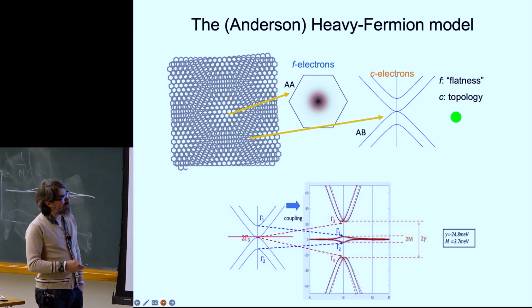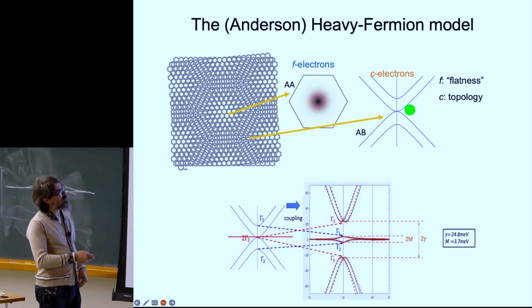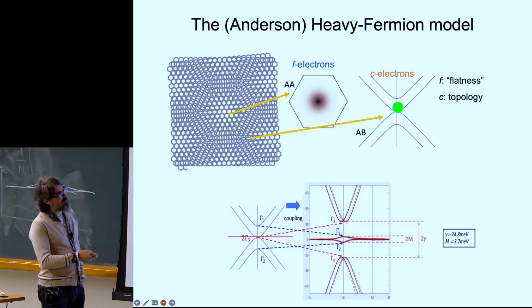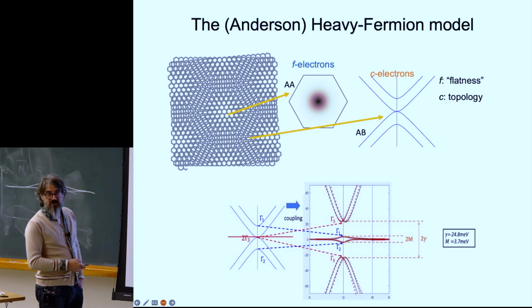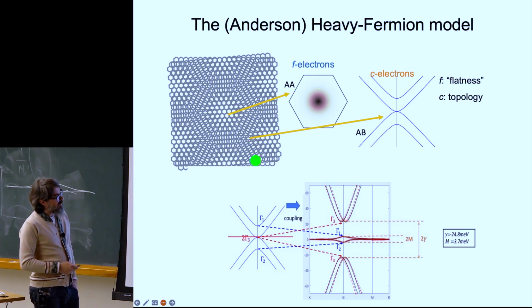And in fact, you can deduce what the delocalized state is. The delocalized state is the one that carries the topology and is given by an AB untwisted, we call it C electron because it's just the conduction electron, the one that does all the conduction. So it's an untwisted C electron, AB, and you know that this has a double vortex here. Okay, and this double vortex is topological. This is a topological semi-metal. You cannot break this double vortex without killing some of the symmetries of the system. So this topology, the topology of the bands, has now been pawned off on the topology of the dispersive fermion.